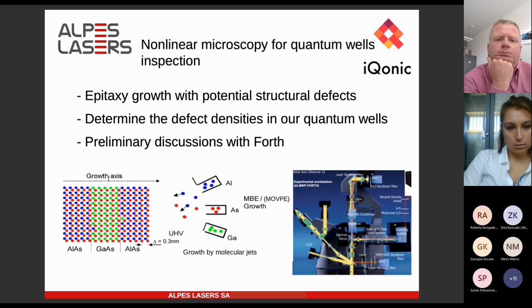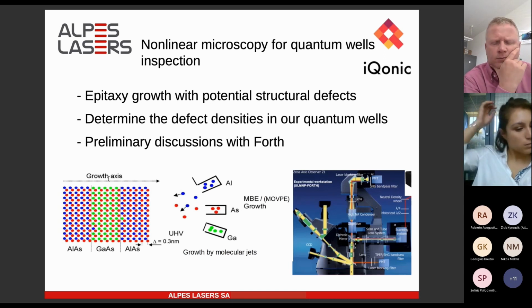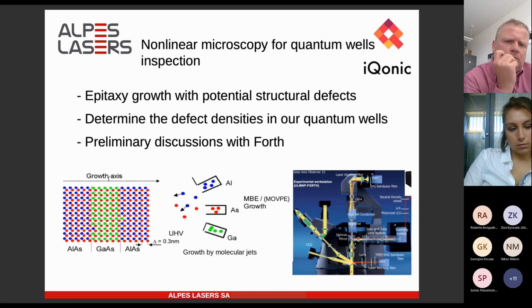The second possible improvement that we can have in the future is nonlinear microscopy for quantum well inspection, because the first step that we do for fabrication is this epitaxy. So we grow some semiconductor layers. They are very thin, about 10 nanometers. And very often we have some defects. We have a distribution of defects inside the structures, for example, dislocations or other kinds of defects.